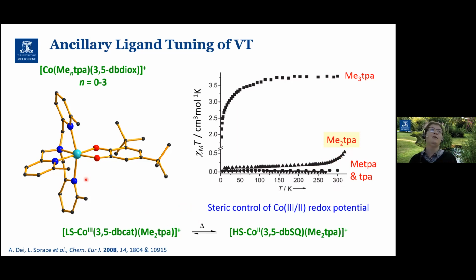So a way of thinking about that is as you're putting these methyl groups here, you're increasing that bulk around the cobalt coordination environment. And the best way for the molecule to accommodate that is being in the cobalt-2 form with those longer bond lengths.